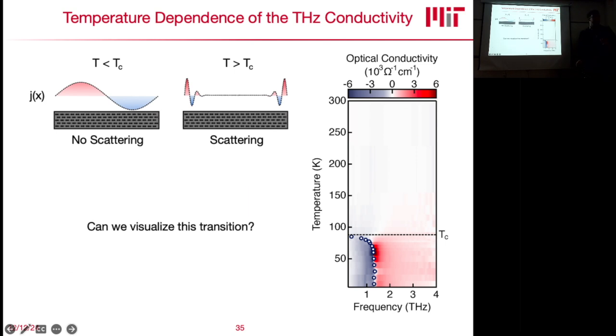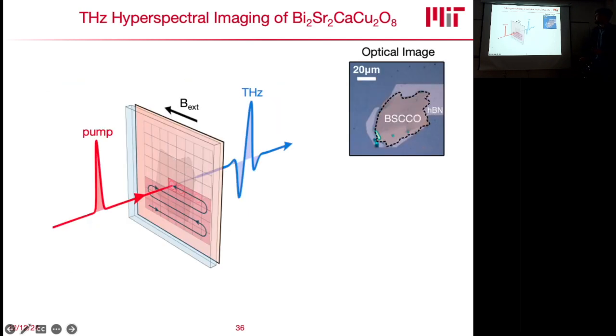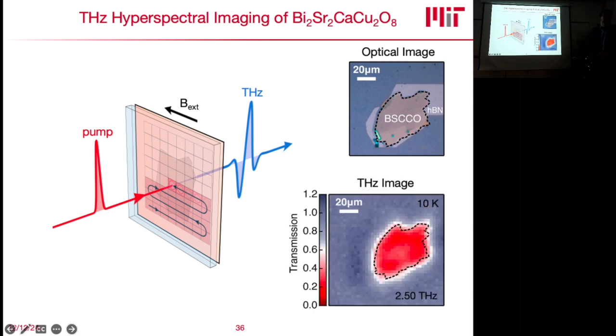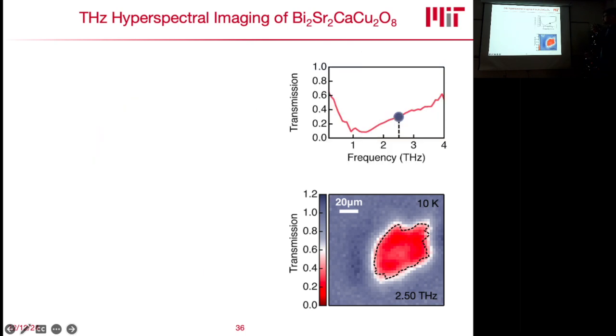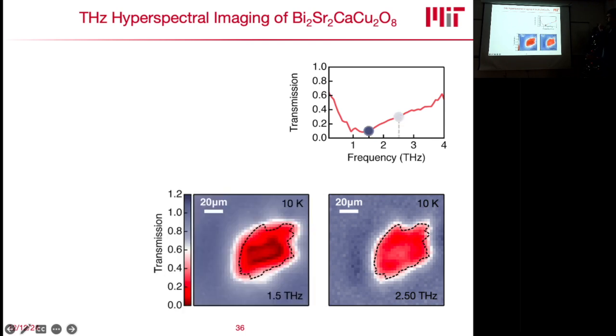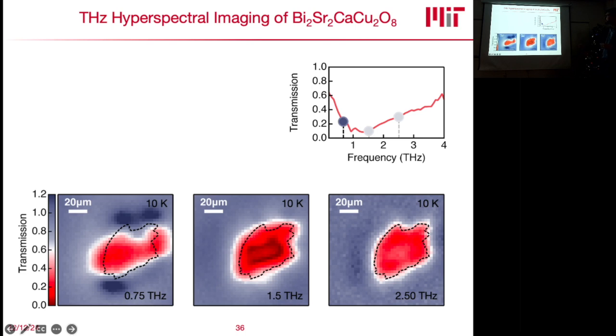And so now the question is, can we visualize this? Is this possible? Of course, we can now just start scanning our excitation beam across the sample and do all of these experiments in a raster scanning pattern. And this is our image. We picked 2.5 terahertz here, and it looks pretty similar to what we see in our optical microscopy image. This is now a terahertz image, and each of these pixels has full spectroscopic information. So we can go from 2.5 terahertz to 1.5 terahertz, where we see this resonance. We can start seeing these patterns inside, down to an extremely low frequency of 0.75 terahertz, where it looks dramatically different.